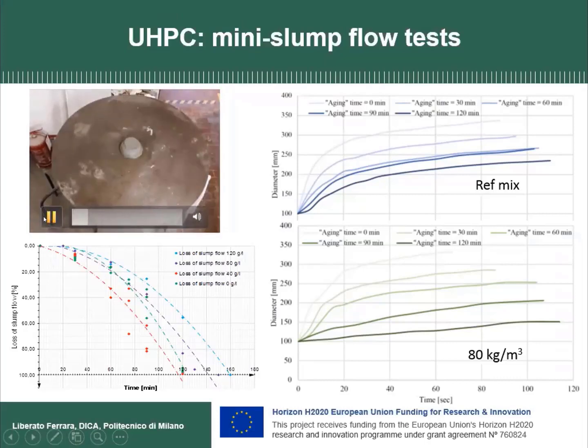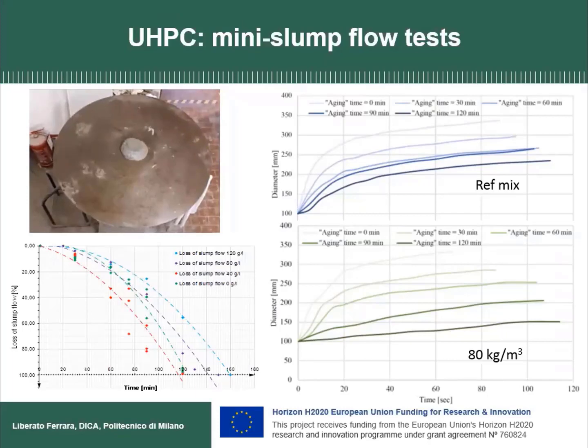This is a movie of a slump flow test. We also developed a small frame to keep a camera at 90 degrees, really filming the slump flow test vertically, and then we processed the movie. We are performing some fluid state simulation, some computational fluid dynamic simulation. You can see how the slump flow versus time curve evolved, but we also calculated, as a preliminary assessment, the evolution of the rheological properties.